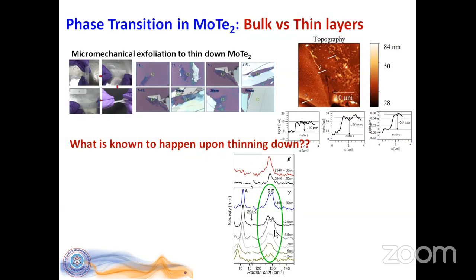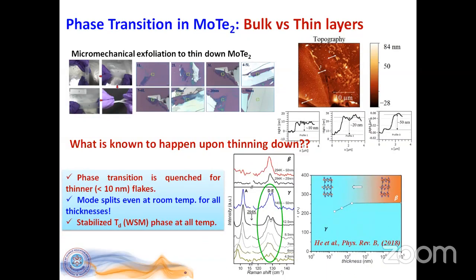So which is what they established. That means if we thin it down, even at room temperature, it goes to the orthorhombic phase or the Td phase, which is the Weyl semi-metallic phase. And this was the PRB article which they showed. And the claim was that anything less than about 10 nanometers or so, the phase transition is completely quenched, which basically tells that the Td phase or the Weyl semi-metallic phase is stabilized even at room temperature and all temperatures rather. So that is something which is known in the literature.